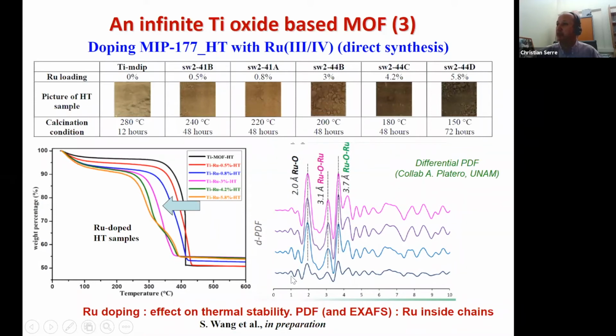And to be sure that the ruthenium was inside the framework and not extra-framework, we carried out several characterization techniques such as EXAFS, for instance, and also differential PDF analysis that was done in collaboration with Ana Platero from Mexico. And you can see here that they observe ruthenium-oxygen distances that are exactly the ones expected from the crystal structure, in addition to ruthenium-ruthenium distances that are also similar to the ones we have in the crystal structure. So all the techniques go in favor of the ruthenium being inside the framework and not outside the framework.